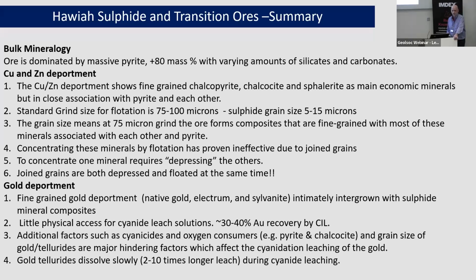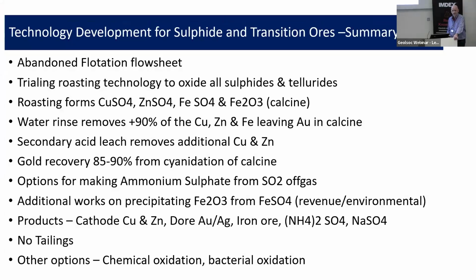So we've been pursuing the roasting test work at Alfred H. Knight. At Alfred H. Knight we get probably 90% of everything that's in there. So it's copper, zinc, silver, gold. And if we precipitate the iron from iron sulfate, because you can't put iron sulfate into a tailings dam because you have to neutralise it first. So if you selectively precipitate it, you can generate both iron oxide and sodium sulfate, both of which are saleable, which means 0 tailings dams.